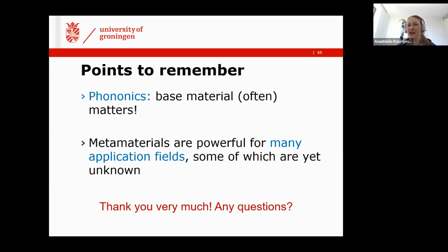Yes, thank you, Fernando. Yeah, I didn't know that it's possible to eliminate this dependence by pre-stressing the material, but it can indeed be very interesting, because when you pre-stress, you increase the elastic modulus of the material, and this indeed will change the full behavior of this module, depending on the temperature, and also on strain rate. And it would be interesting to characterize it, considering that current low-cost manufacturing techniques allowed